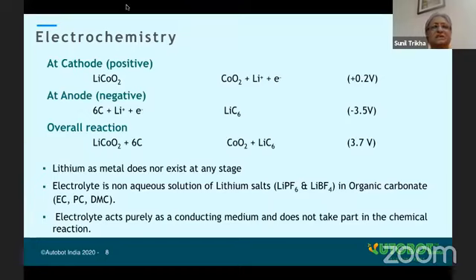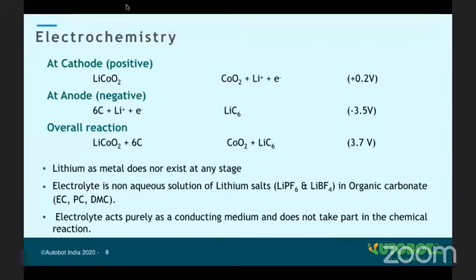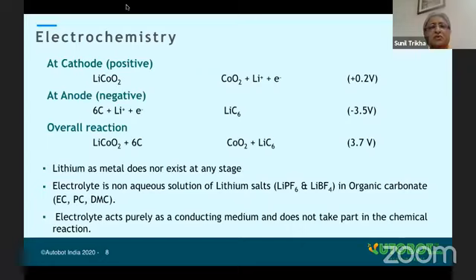Okay, when you charge, lithium cobalt oxide liberates lithium ions. And then when you discharge, it again becomes lithium cobalt oxide. On the anode, carbon combines with lithium ions and makes lithium C6, LiC6. So in the total process, there is no lithium metal. So there is no danger of lithium. These are layered materials, intercalating materials.